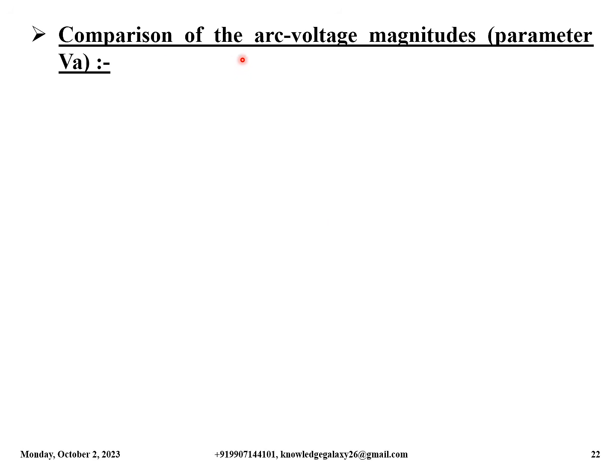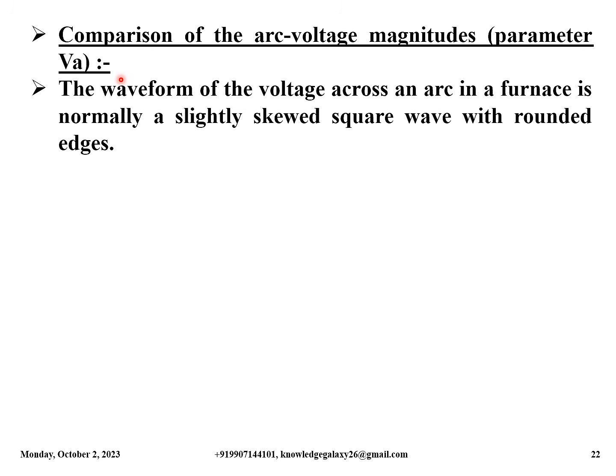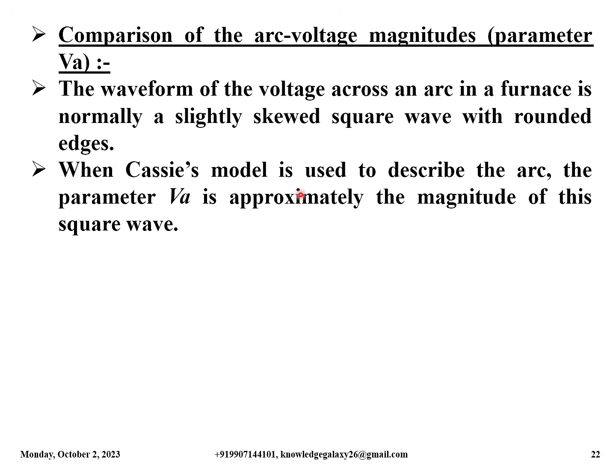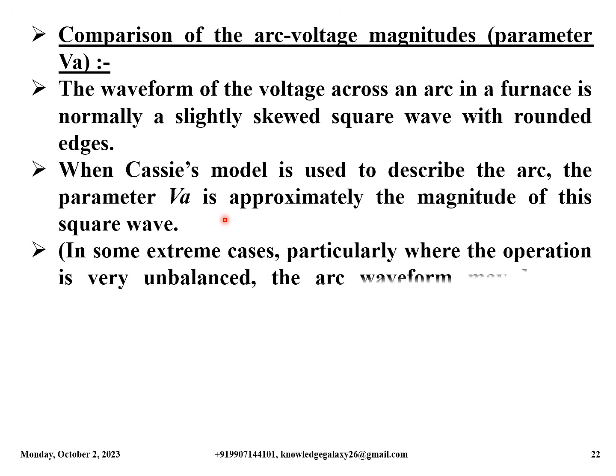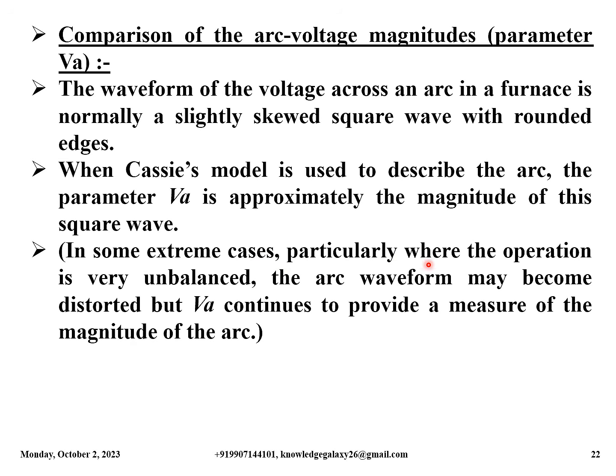Now let us have a comparison of the arc voltage magnitudes, that is parameter VA. The waveform of the voltage across an arc in a furnace is normally a slightly skewed square wave with rounded edges. When Cassie's model is used to describe the arc, the parameter VA is approximately the magnitude of this square wave. In some extreme cases, particularly where the operation is very unbalanced, the arc waveform may become distorted, but VA continues to provide a measure of the magnitude of the arc.